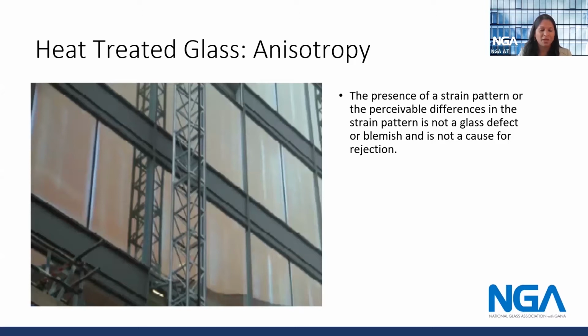So the heat treating process is when you take the annealed glass and heat it up to approximately 1150 degrees Fahrenheit. And the reason why you do so is in order to get the required resistance to the thermal and mechanical stresses, so that way you have safety glazing in the tempered glass. So after it's heated up, it needs to be quenched down to cool down the glass.